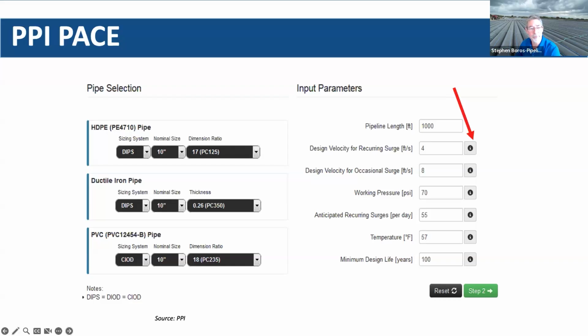So it's going to look at your different pipe sizes and different pressure classes. And this is a great tool for making sure you pick the right pressure class for each material. Remember, one of my biggest pet peeves on this for people to remember, all pressure class definitions are different for every material. So if you use pressure class defined by ductile iron, it's not the same as defined by PVC and not the same as defined by polyethylene. So you can't use pressure class for pressure class comparison and have a successful design. PPI PACE will help you with that.